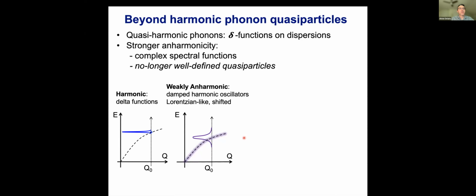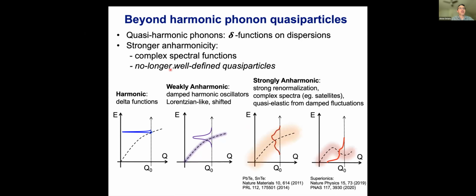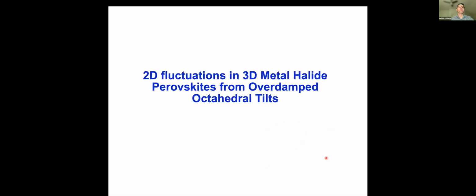However, there are some, I would say, perhaps less well understood but very interesting effects that happen when you have a very strongly anharmonic potential energy surface in softer, somewhat floppy materials. And there we really lose the intuition of this quasi-particle and Lorentzian peaks in the spectra. We can have very complex many-body effects in the spectral functions that we can start to hope to understand based on more advanced modeling, and I'll show a little bit on that. In extreme cases, you can lose vibrational dynamics entirely and have more of a relaxational behavior that then shows up at very low frequencies. And we indeed see some of that in the metal halide perovskites, as I'll illustrate in this presentation, and also in materials such as superionic conductors that we're also working on, but I won't have time to discuss today. So let's focus on the metal halide perovskites first.